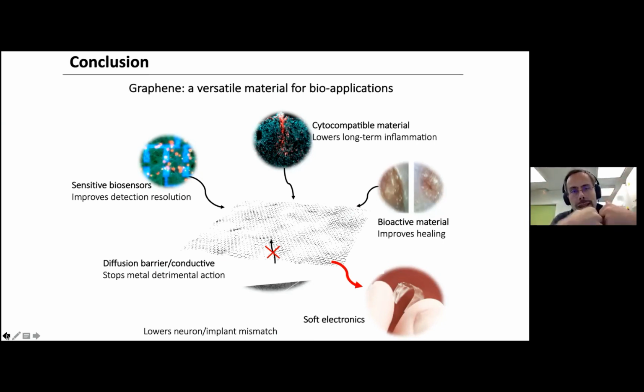Without this, the system is sensitive to ions, and so you have basically an ion sensor, which is not selective. But we start with that because this is the biocompatible material. This is the easiest way. We've done all the biocompatibility with that material. So any change of ion composition will be sensed globally. So we have a signal which is not exactly a pH meter, but more like a mixed pH ionic meter.